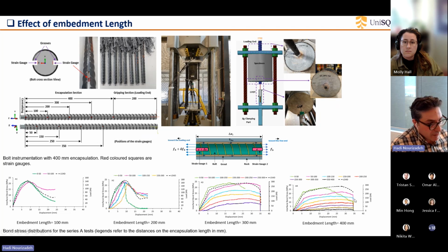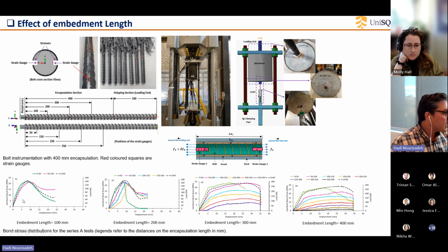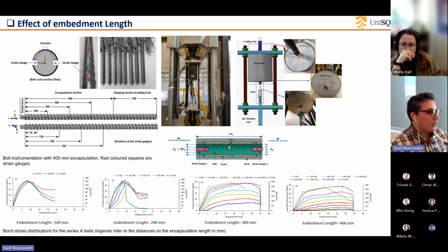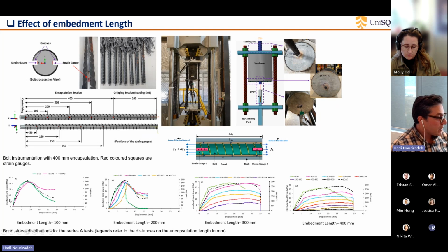So here we have different diagrams, which may be a bit confusing, but generally speaking, in the vertical axis we have interfacial bond stress. Interfacial means the interface between the bolt and the grout, or the encapsulation agent. Again, we have different encapsulation lengths, including 100, 200, 300, and 400 millimeter. How could we calculate these interfacial bond stresses? This is calculated by considering the strain values we got from those strain gauges that we installed along the encapsulation lengths. The difference between these strain values can give us the interfacial bond stress.